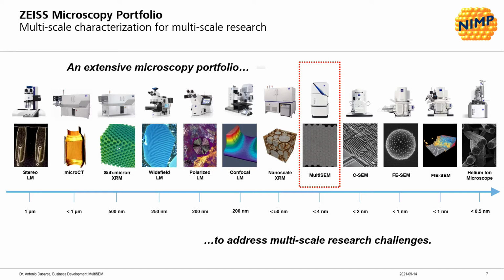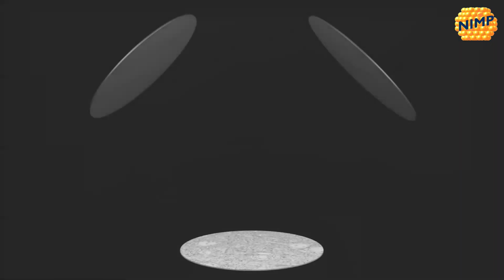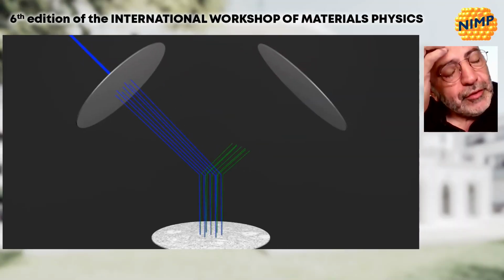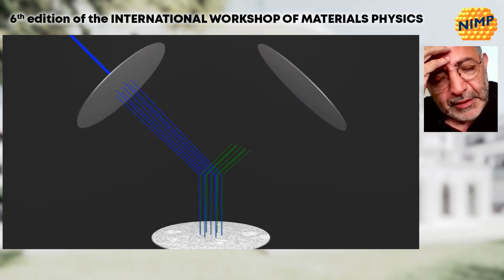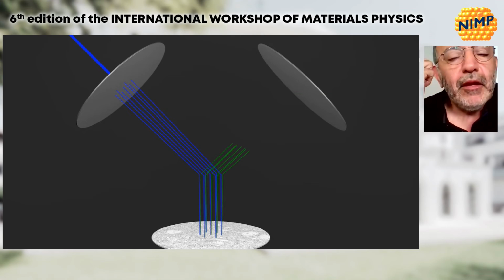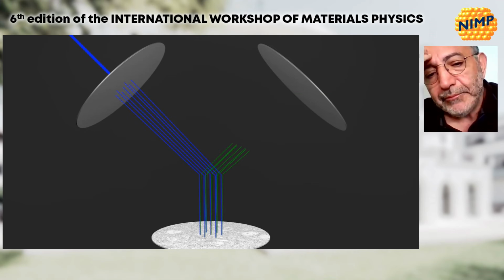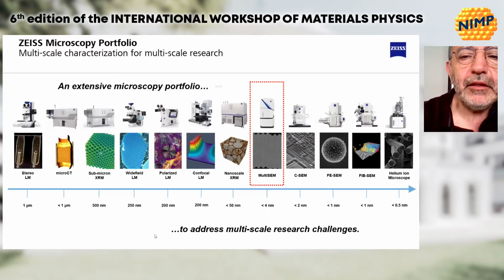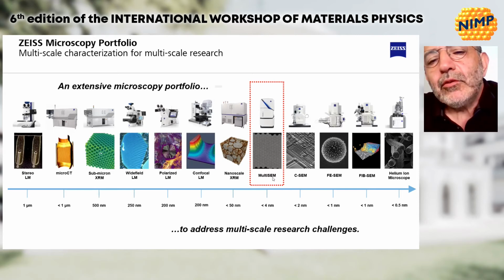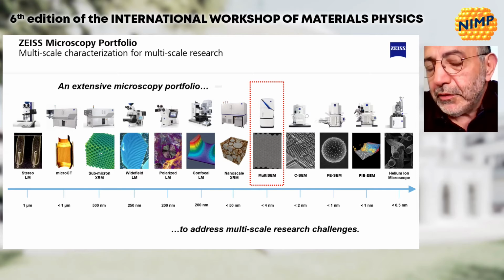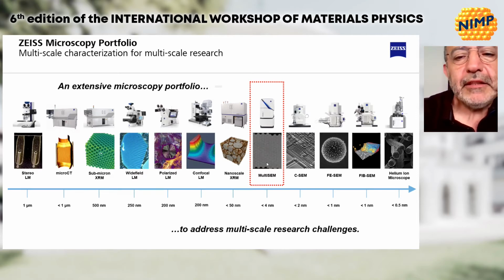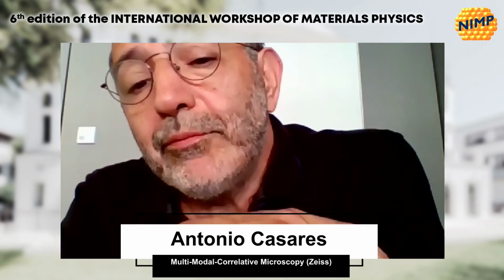You can very easily imagine that if you want to image a cubic millimeter sample with a single beam at, let's say, a couple of nanometers, 2, 3 or 4 nanopixel, the scanning of those samples at this resolution will take years. The only way to bridge this and bring the scanning time to a reasonable level is to use a so-called multi-SEM. Multi-SEM is a field emission electron microscope, as you know very well, but instead of a single beam, it uses a bunch of up to 100 beams in parallel. Then you can reduce the scanning time by up to 2 orders of magnitude compared to a single-beam SEM. And this is a key instrument for